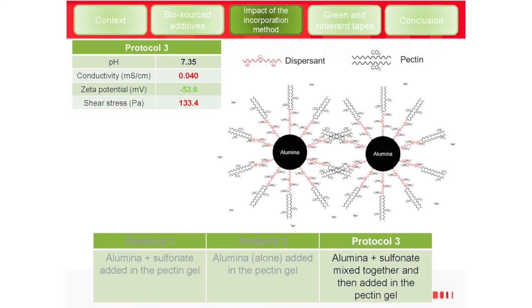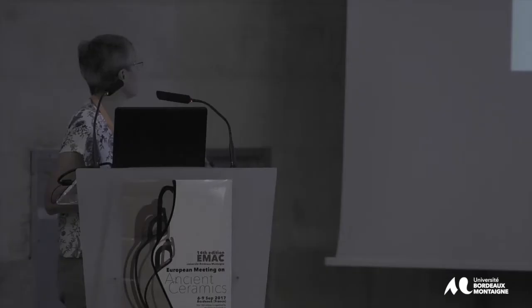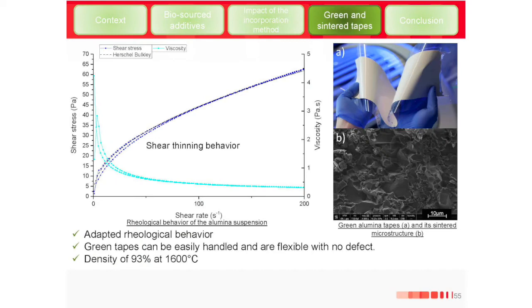So the best protocol was the first one, and here's a typical shear stress as a function of shear rate curve: we have a shear thinning behavior and a viscosity which drops down to values which are quite compatible to obtain a ceramic tape. After sintering at 1600, we have a density around 93%.